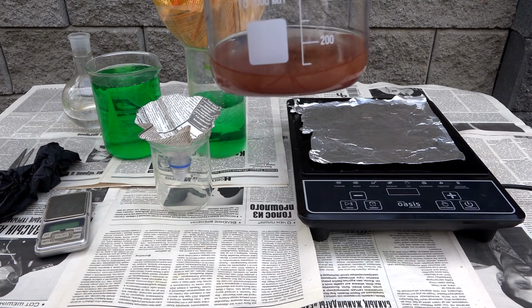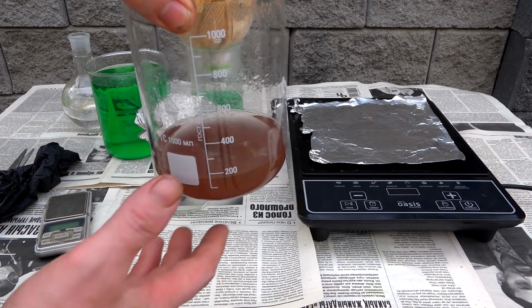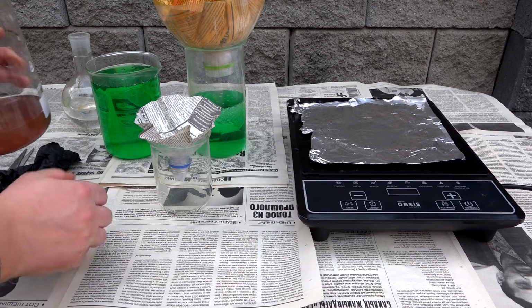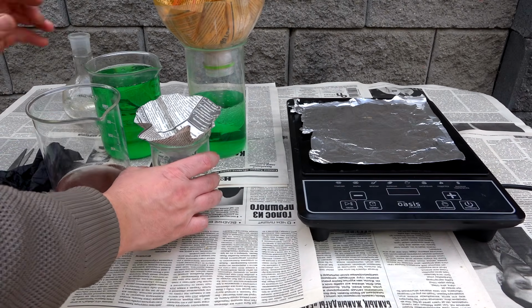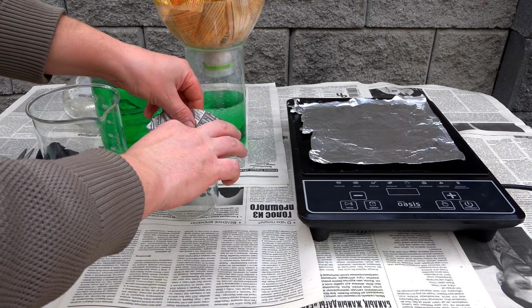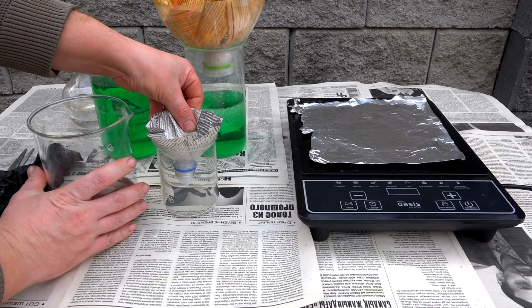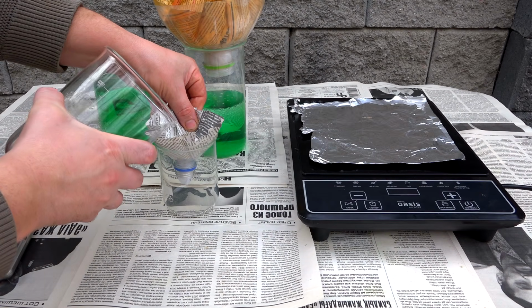It took 30 minutes, but I'm satisfied with the result. I obtained a clear solution. This precipitate can be filtered through paper and then melted. The white cloud has dissolved, and I've noticed the precipitate has become lighter.